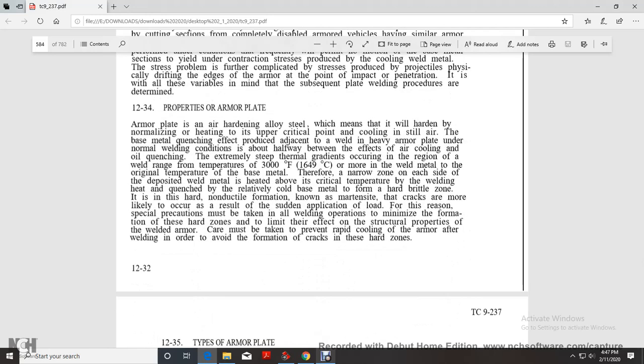Armor plate is an air hardened alloy steel, which means it will harden with normalizing, heating to the upper critical point and cooling in still air. The base metal quenching effect produced adjacent to the welding of heavy armor plate under normal welding conditions is about halfway between the effect of air cooling and oil quenching. The extreme steep thermal gradients occurring in the region of the weld range from a temperature of 3,000 degrees Fahrenheit or more in the welded metal to the original temperature of the base metal.